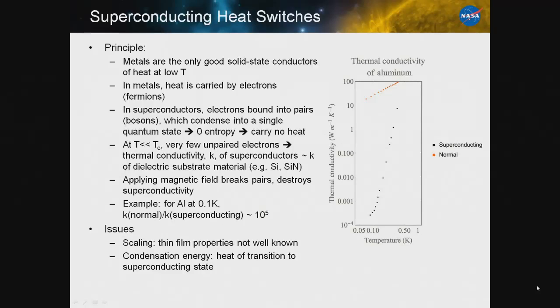On the other hand, you can apply a magnetic field greater than the critical field, and you can break the pairs, destroy the superconductivity, and switch the thermal conductivity to the normal state thermal conductivity. And for aluminum, you can get about a factor of 10 to the fifth at 100 millikelvin in your thermal conductivity ratio.